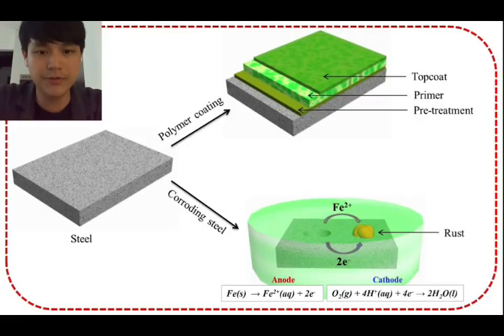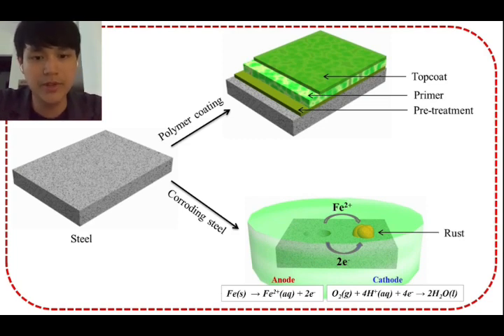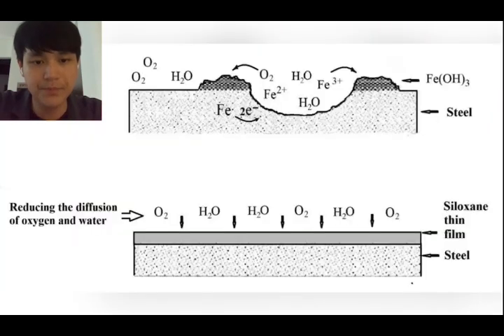The many protective properties of material coatings are determined by the strength of adhesive bonds at the metal-polymer interface. And since organosilane molecules are bifunctional, this makes them a very great material treatment choice. By bifunctional, it means that the molecules can simultaneously interact with both the surface of the material and the coating. So for example, by treating a material with organosilane aqueous solution and applying a polymer coating, the positive properties of the coating will be significantly improved.